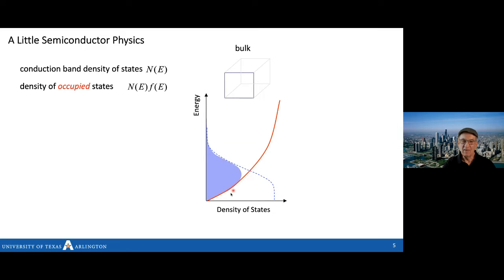The outline of this is the density. And if we integrate that, we get the density of carriers, which is now the density of states times the probability that it's occupied over the whole range of energy from the conduction band to infinity. Why am I telling you this? Because this part here, N, corresponds to the current that we put into this. So this is the connection between the physics inside the device and what we control with a knob on the outside. So this in an LED basically is the device current.